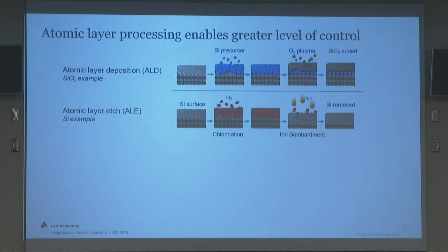It's similar, in reverse, for the atomic layer etch process. So if you want to remove silicon, you can bring in, say, a chlorine layer, and that can be a gas or often a plasma. And then you bombard it, in this case with argon ions. You can think of ions from a plasma as mini cannonballs that physically strike the surface. They will have an energy greater than the binding energy of that atom to the surface, and they eject it. So you remove the reacted silicon bonded to the chloride, but not the silicon bonded to itself, the underlayer of silicon. So you have to control that energy very precisely.